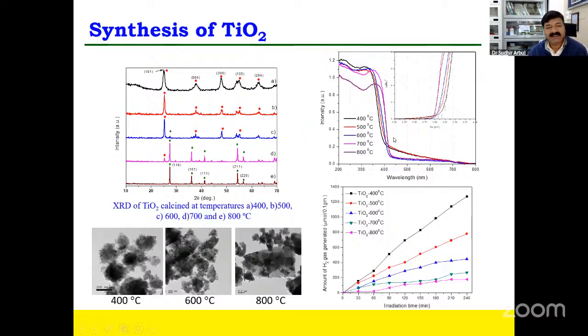Another one is here, the material is the same. Here we prepared the TiO2 using the sol-gel technique and we heated this from 400 to 800 degrees centigrade just to see what kind of structural behavior is happening in this TiO2 and what is its change in the optical properties. So here what we observe, up to 500, the anatase phase is stable. Anatase at 25. If you heat it further, small peaks are arriving at 27. So this is the rutile phase. This anatase phase starts converting into rutile phase.